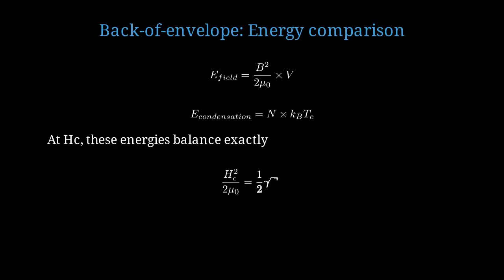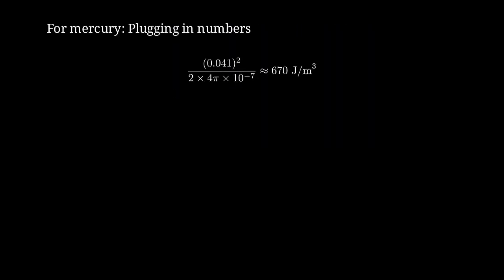We can write this balance as H sub c squared over 2 mu 0 equals 1/2 gamma T sub c squared, where gamma is the Sommerfeld coefficient representing the electronic specific heat. For mercury, let's plug in numbers. H sub c is 0.041 Tesla at 0 Kelvin. This gives a magnetic energy density of about 670 joules per cubic meter. 0.041 squared divided by 2 times 4 pi times 10 to the minus 7, which equals approximately 670 joules per cubic meter. This is the condensation energy density.